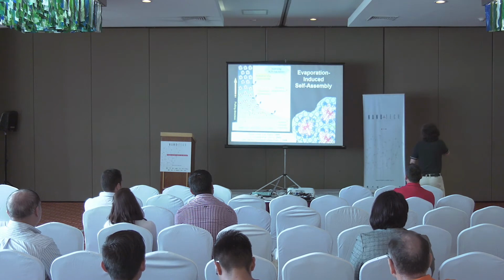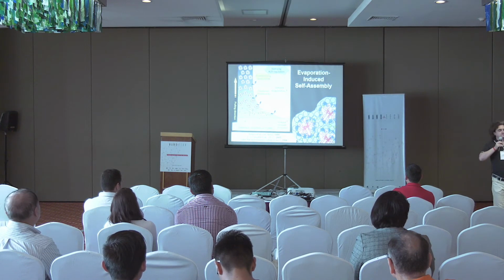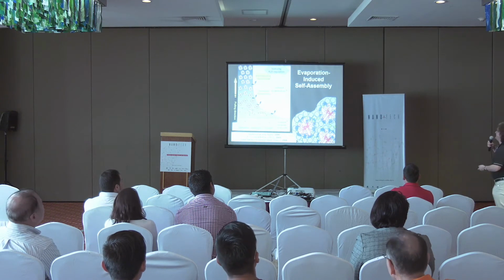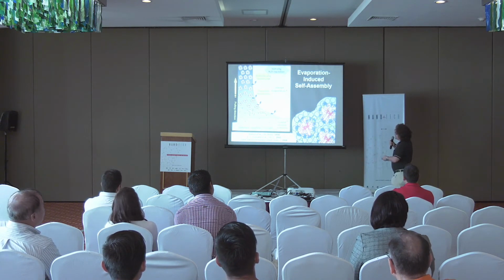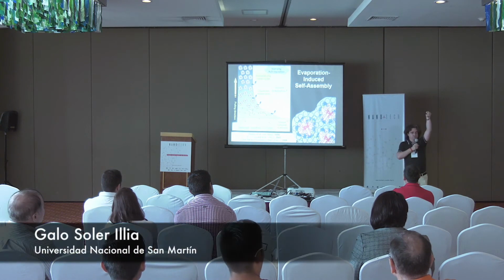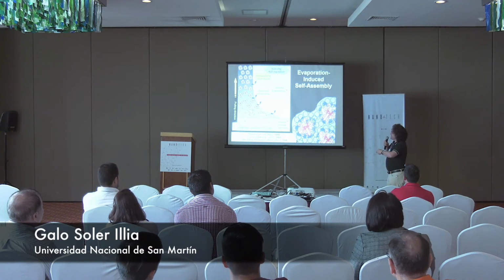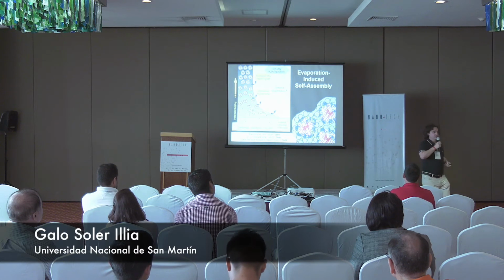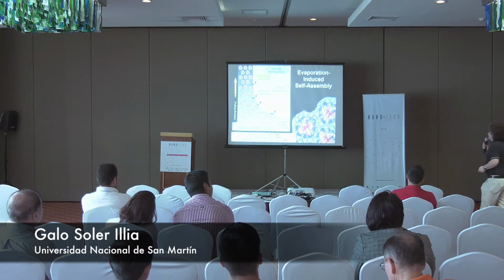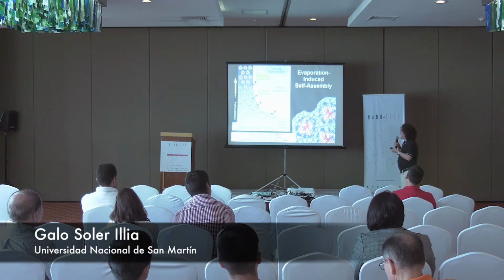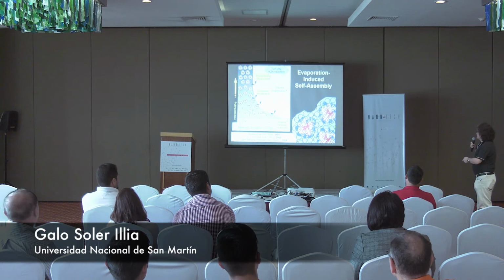information. We spent several years trying to understand how these things formed. And to make a long story short, this is a kind of ballet. You know ballet? This is a dilute solution. The substrate enters here, and when you pull the substrate outside the solution, you form a liquid film. The liquid film begins to evaporate because there is a volatile solvent. Micelles begin to form, micelles begin to pile up, and eventually form an organized lyotropic structure, a lyotropic liquid crystal, with some organization. The image we have in our heads after doing hundreds of experiments in synchrotron, using different techniques, which took a long time. Remember, short story, was this.